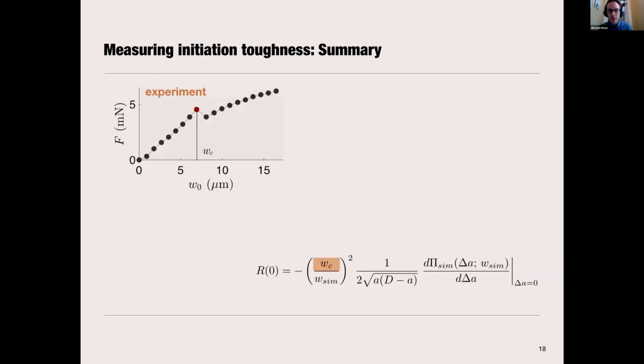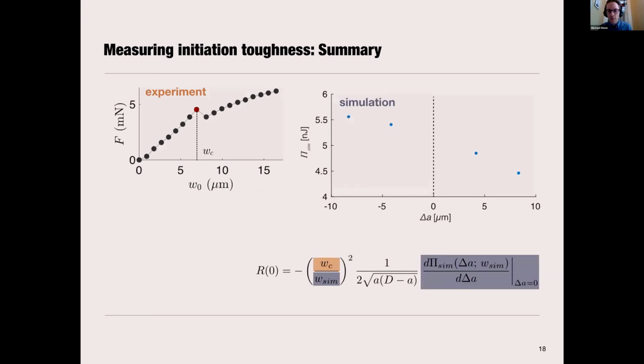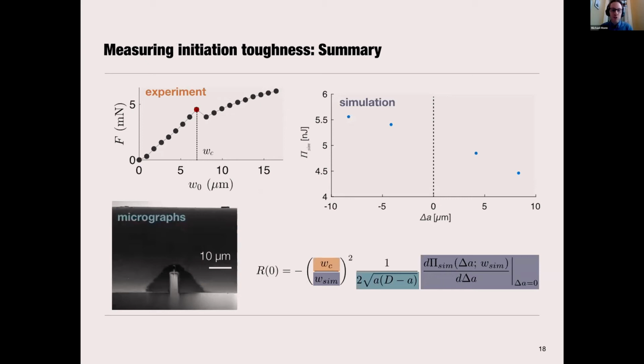So in our experiment, we measure the deflection of our cantilever at the initiation point. From our simulation, we use a 4-point central difference to get a change in potential energy with respect to a crack increment. And we measure these geometric quantities from the micrographs.